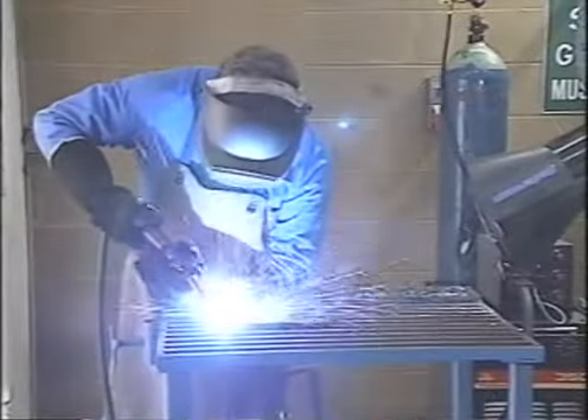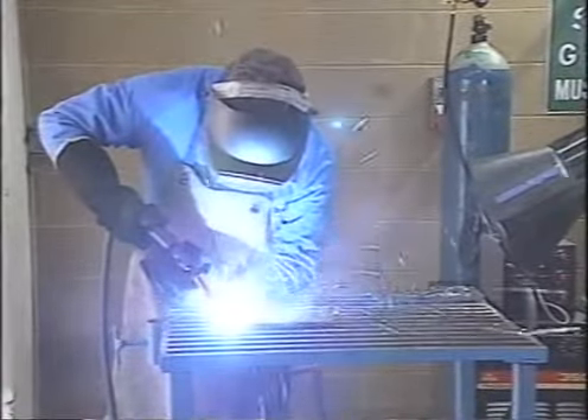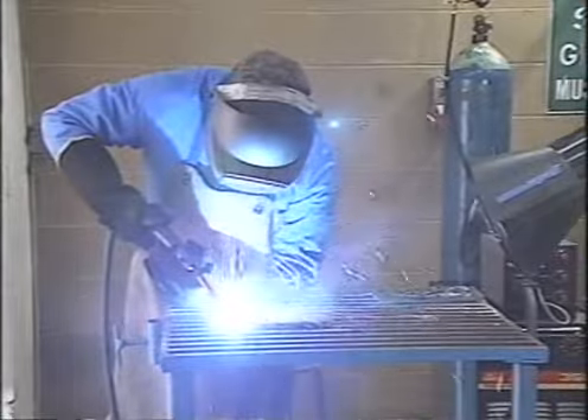After the arc has been established, move the gun forward in the forehand direction. If you're right-handed, you should move the gun from right to left to ensure that you have a good view of the weld pool. Of course, if you're left-handed, the opposite applies. Make sure you keep the nozzle close enough to the work to maintain the arc. Excessive stick-out reduces the effect of the shielding gas and may cause porosity in the weld joint.